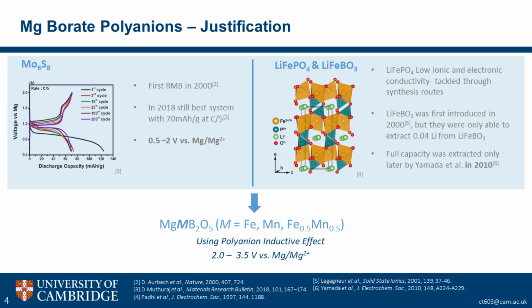And so what we decided to work on was magnesium transition metal pyroborates. We chose the polyanion system because it uses the polyanion inductive effect to raise the theoretical operating voltage of the battery compared to the standard molybdenum sulfide. The polyanion group itself also stabilizes the oxygen, and the boron was chosen as it would offer a lighter system and therefore higher gravimetric capacities.